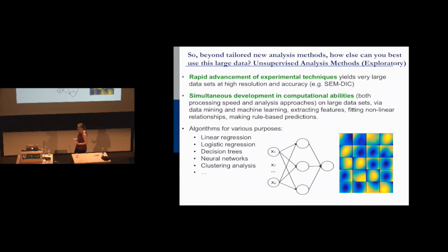And what we want to do is look at how the microstructural landscape around you is really important, right? We showed that. It's not just the orientation of a grain, it's the local surrounding system. So what's bad about a local surrounding system that would cause you to have a lot of damage? Well, when we look at just the pictures, like I showed you, we couldn't find anything. So we're taking so many pictures, we have to use these unbiased algorithms to pull out a pattern recognition of what's causing damage.